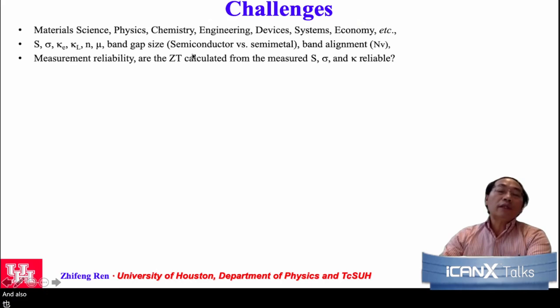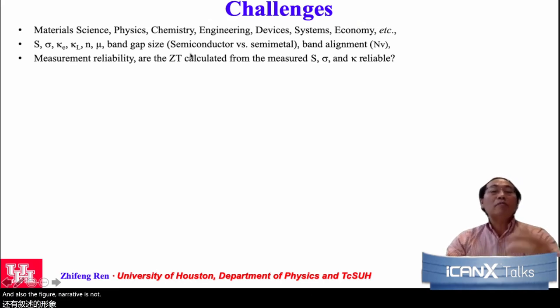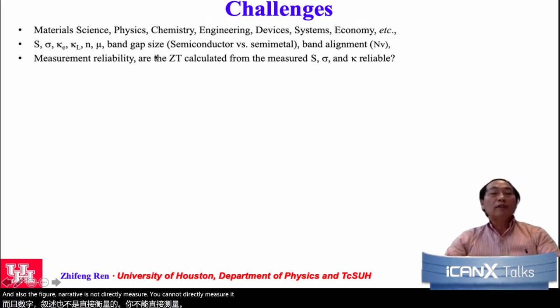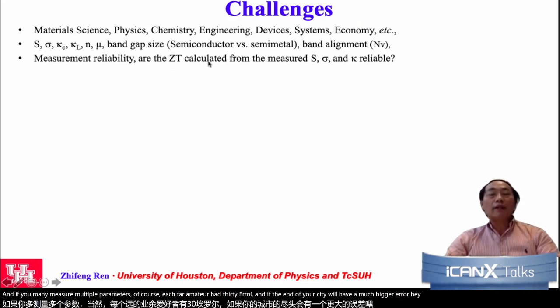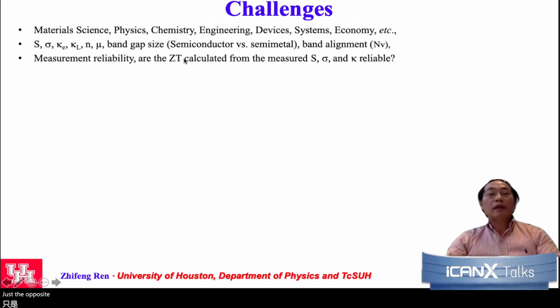And also the figure of merit is not directly measured. You cannot directly measure it. You measure many of those individual parameters, and then you do a calculation. And if you measure multiple parameters, of course, each parameter has a certain error. At the end, your ZT will have a much bigger error, which is why very often you have to find other ways to verify whether it is as high as you are reporting or not, which is why device measurement is important.